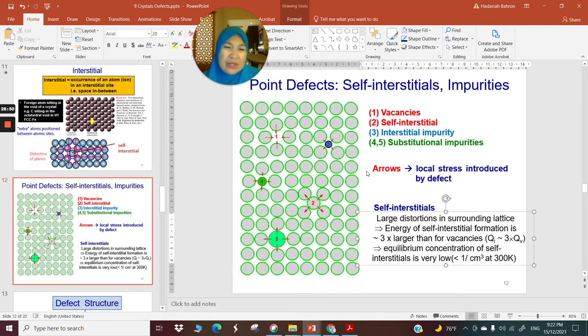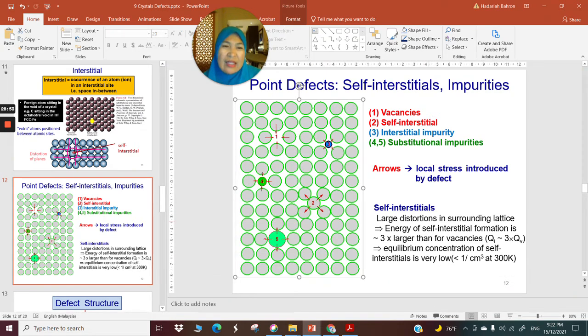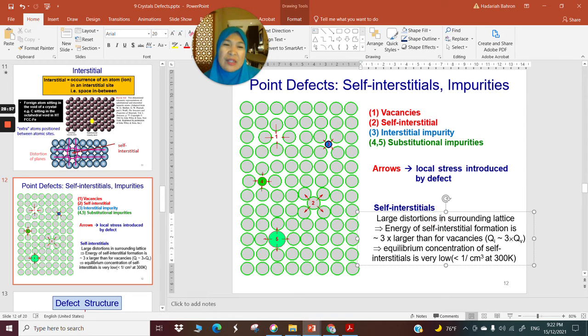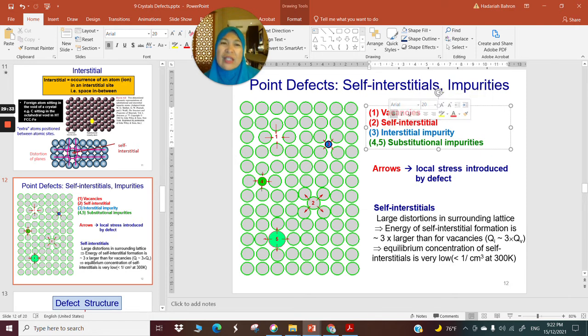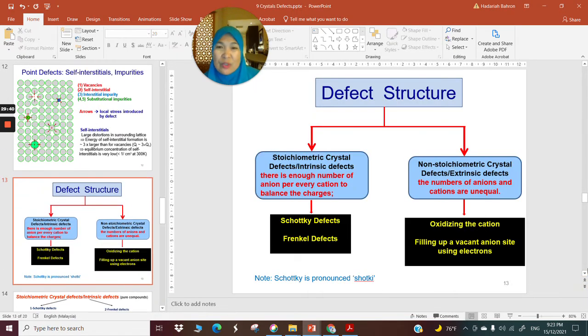So self-interstitial, which is this one here, introduces a large distortion in the surrounding lattice, where the energy of self-interstitial formation is about 3 times larger than that of the vacancy. Therefore, the equilibrium concentration of self-interstitial is very low. It is less than 1 per centimeter cube at 300 Kelvin. So these are the 4 types of point defects that you might encounter: vacancies, self-interstitial, interstitial impurity, or substitutional impurity. I hope you can distinguish between the four.